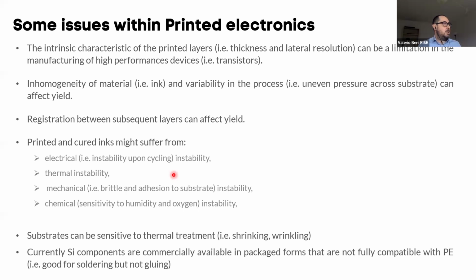For example, materials that can shrink or swell as a function of, for example, heat treatment could bring some issues in this regard. Printing and curing inks might suffer from electrical instability. Could be thermally unstable. Could be UV unstable. For example, some of the semiconductive polymers are sensitive to UV light. Can be mechanical, for example, can be brittle or have poor adhesion, but also can be sensitive to chemistry, for example, humidity, oxygen, and so on and so forth. And of course, the substrate can be sensitive to thermal treatment.